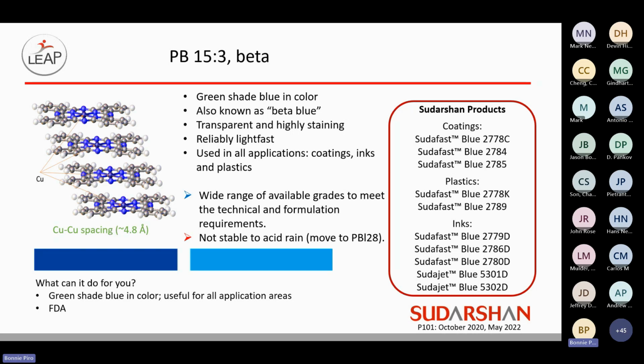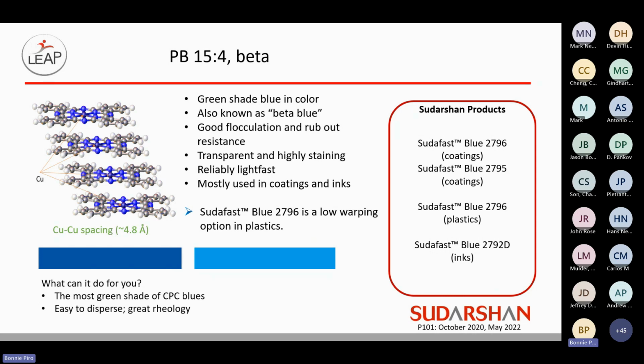Again, same idea that I talked about earlier, where the finishing techniques chosen can shift those performance areas. The whole CPC blue class of pigments are not going to be stable for acid rain, so this is another area where the Pigment Blue 28 can be helpful. And then lastly, the 15-4 blue is the most green in color space. Again, primarily used for liquid coatings because of its good flocculation and rub out resistance. However, we've found some good performance with respect to plastics and have a low warping option for this one.